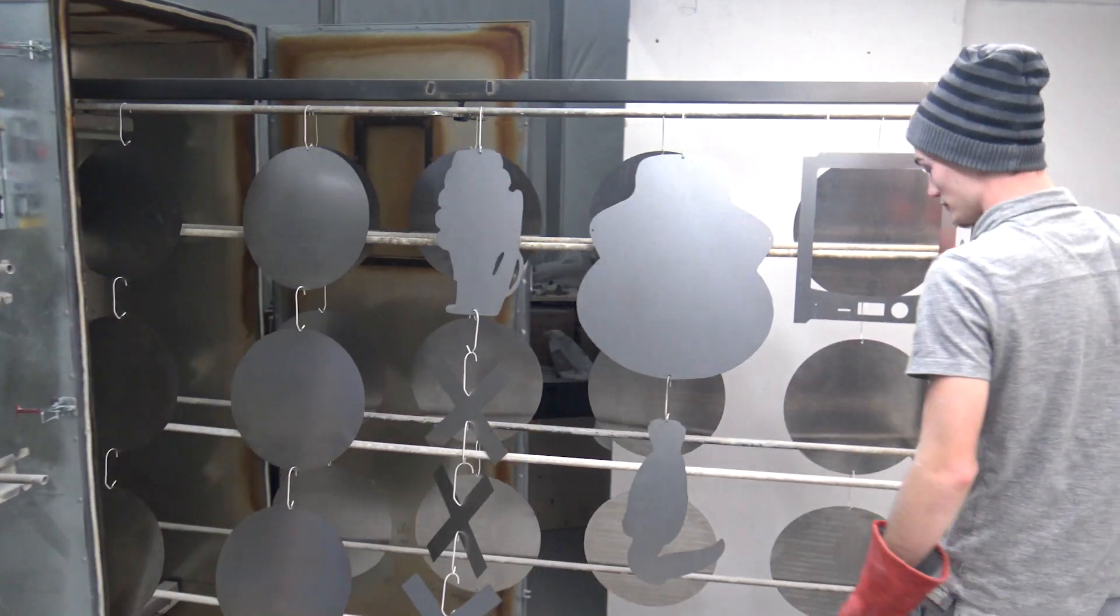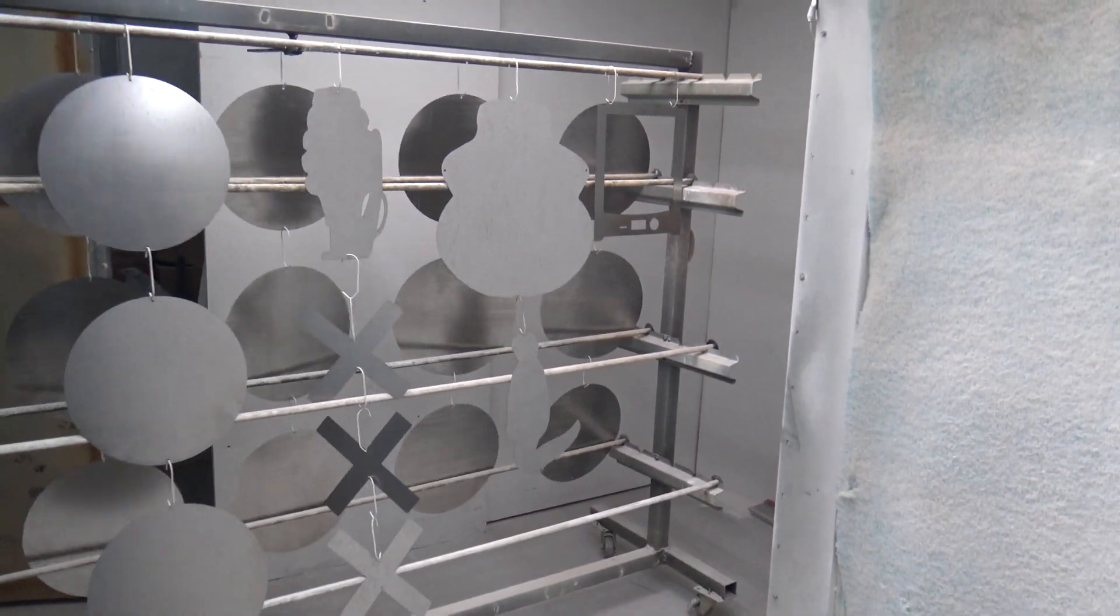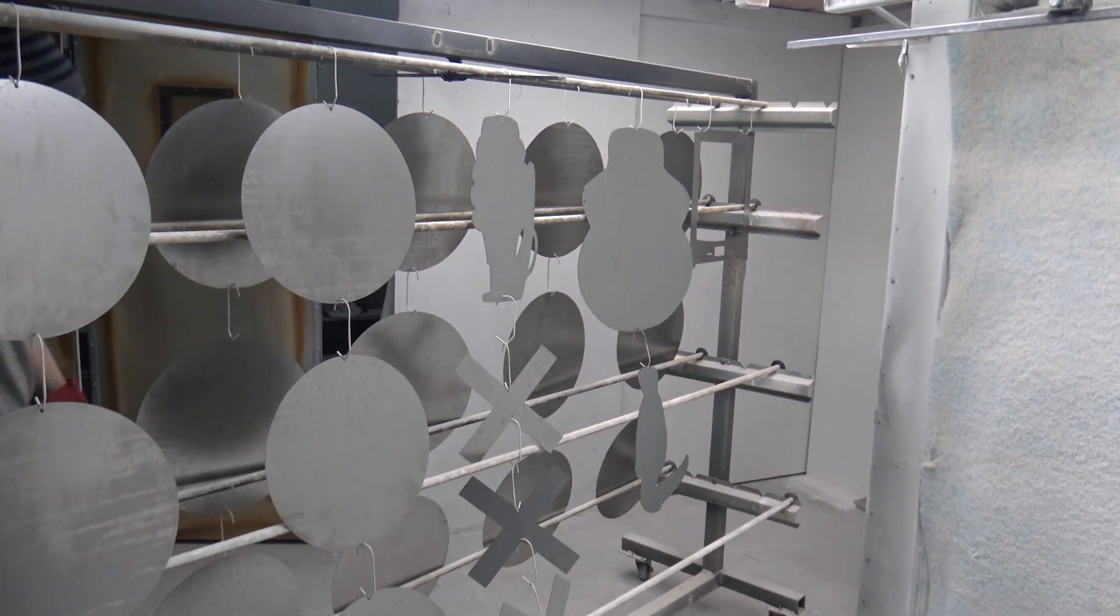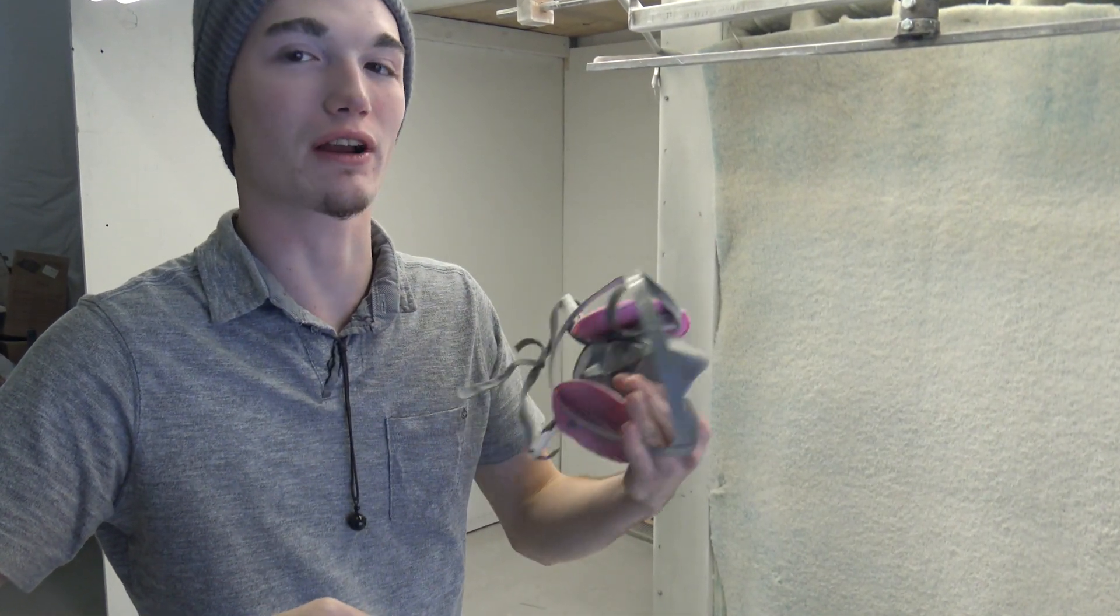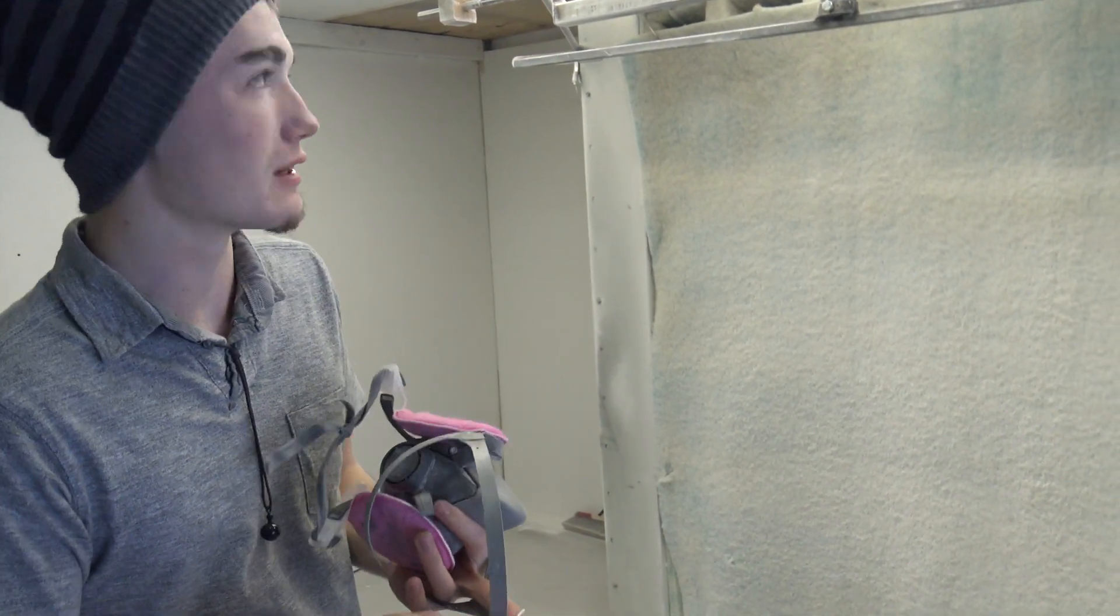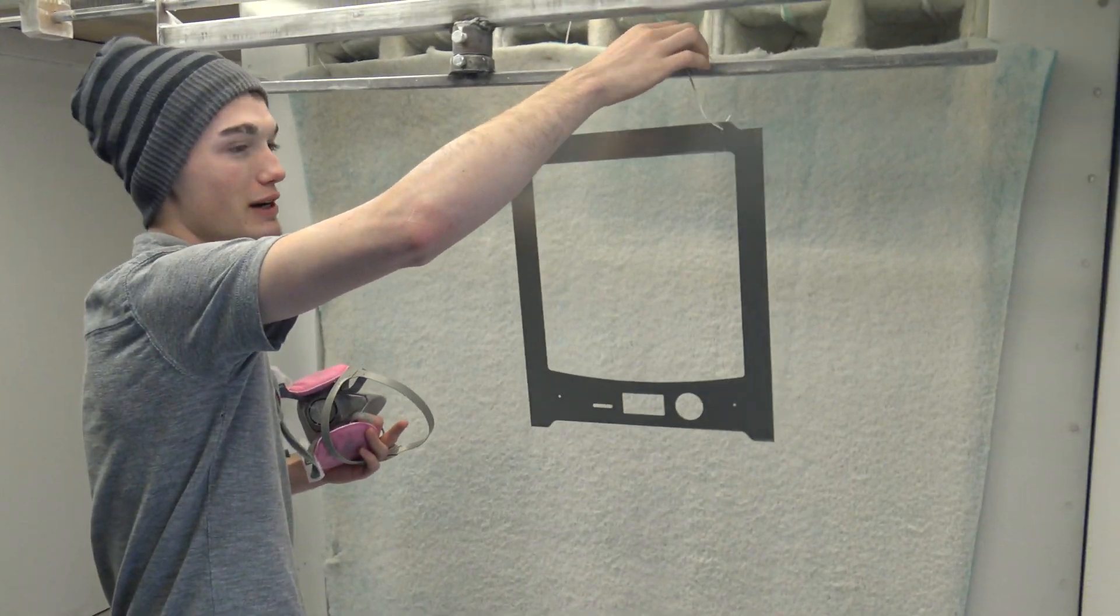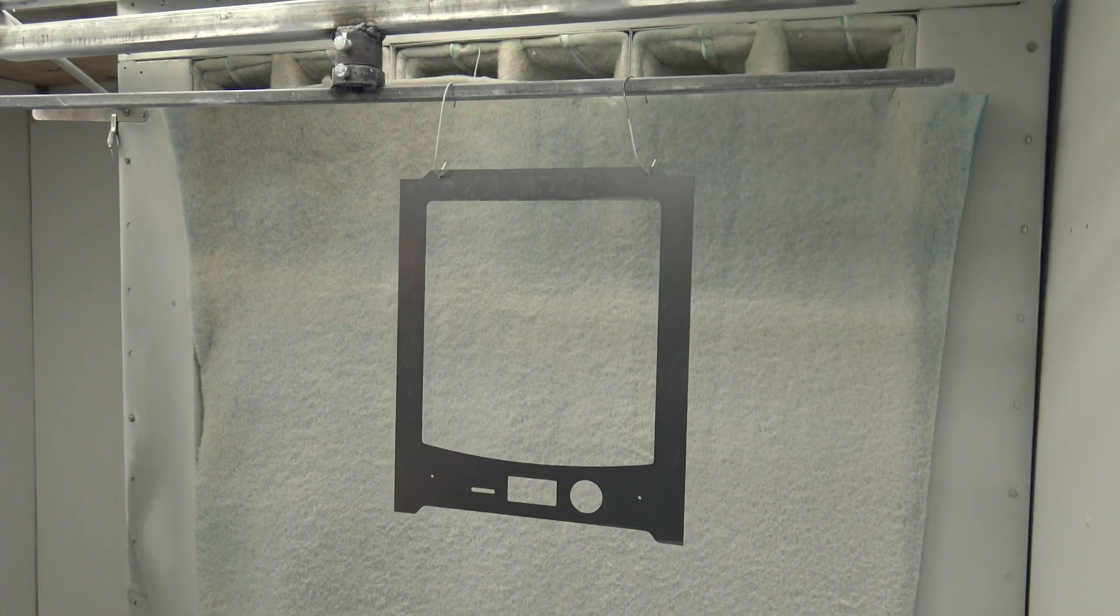I stick it in the oven for about 20 minutes, and usually it has to be at 350 for the cure, but you can stick it in at 400. At like five minutes it'll cure halfway, and then you put the clear coat on it. The clear and the white cure together, so it just depends on whatever time you do. Usually I prefer to do it for 20 minutes. In this step we're just putting on the white.